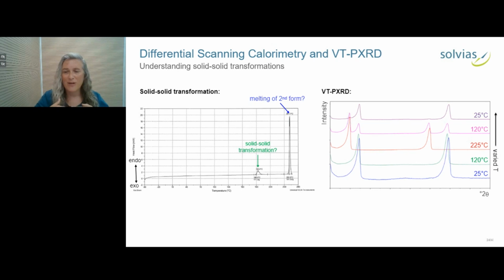So we have an X-ray diffractometer, and we can heat the sample up to different temperatures. If you look at the bottom line in blue, at room temperature, you have one form. I've just shown part of the diffractogram. As you heat it up to 120 degrees, you see slight shifts due to thermal effects on the crystal lattice, but it's the same polymorph. But then if you go up to 225, which is on the other side of this endothermic transformation, you see a different solid form. So this confirms that you have enantiotropically related forms.